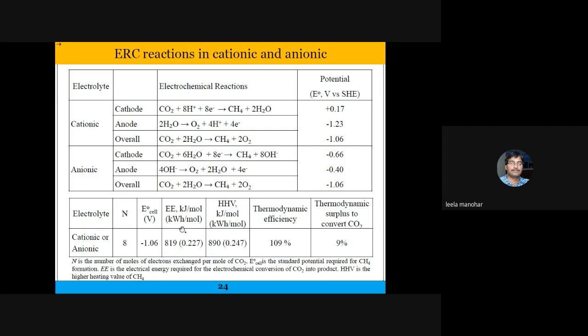But this is what we are getting thermodynamically. If you see the reality, we don't get exactly at minus 1.06. Overall potential required is around 2 to 3 volts. That's what I'm saying: if you develop such an electrocatalyst or electrochemical system in such a way as to reduce the overpotential for the reaction, obviously your thermodynamic efficiency will be in a very good range. We also discussed how your efficiency will change.